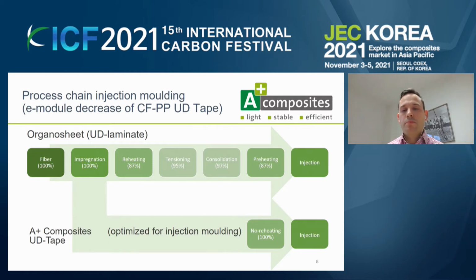If you use the tape, it doesn't matter actually which tape it is. You can use a single reinforcement for a sandwich structure, for example. And if you use the tape from us, there's no reheating or preheating necessary. So you can just introduce the tape into the mold and you do not lose any tensile modulus, for example.